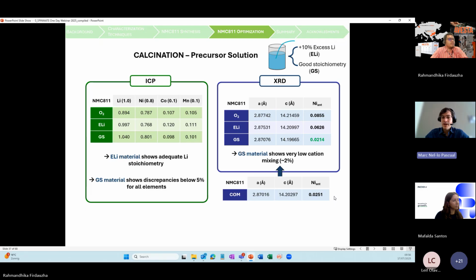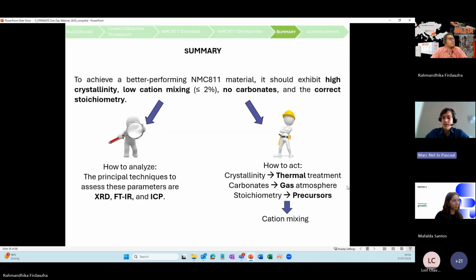So to summarize and end this presentation, let's do just a summary of what we observed. In order to obtain a good performing NMC811 material, you need to have a material with high crystallinity, low cation mixing, no carbonate, and with the correct stoichiometry. So which are the most valuable techniques to be able to assess that? That would be XRD for the crystallinity and for the cation mixing, Fourier transform IR for the carbonate impurities, and lastly ICP for the stoichiometry. And so if you have identified these problems, how do you act? How do you improve those?